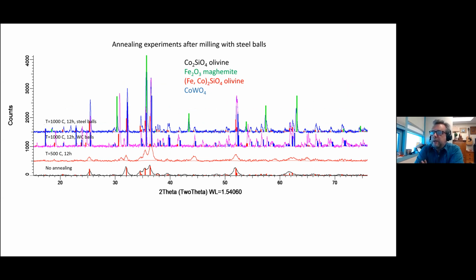We performed these experiments in two configurations. We used either tungsten carbide or stainless steel grinding elements. And in both cases, with the long grinding duration, we noticed that we are grinding off the grinding materials. We are wearing off the jars and the balls. So we had a little bit of iron in the sample that was produced in a steel jar, and a little bit of tungsten carbide in the sample that was milled in a tungsten carbide jar.